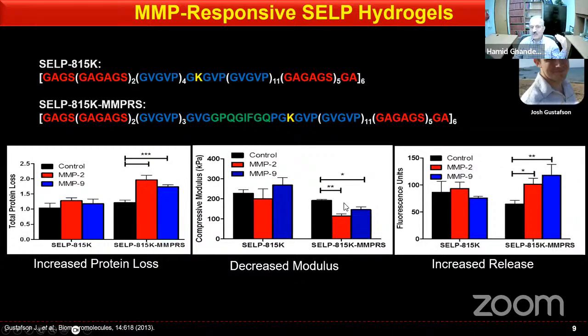This degradation results in lower compressive modulus because the polymer system, the hydrogel system, is sort of falling apart. And so you get less network density. And on the right-hand side, first we looked at the release of certain fluorescent beads to see whether we can enhance the release of these fluorescent beads that are roughly the size of viruses. And indeed, we could see the increased release of these fluorescent beads. So this first prototype of MMP responsive silk elastin block copolymer worked.